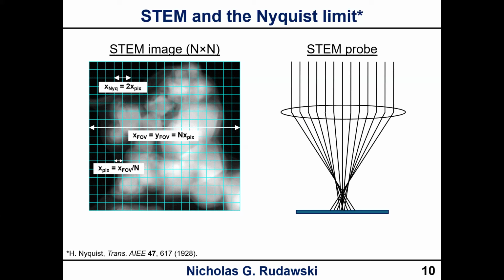So then if we look at this in relation to the probe itself, if we have a probe size here, now of course, this example is a situation where we don't have any CS correction, and you're looking at a case where we don't have proper focus, right? We're over-focused here, and we would need to under-focus to move the plane of least confusion to the sample. But I did this deliberately so you could actually see the probe size more accurately here, okay?